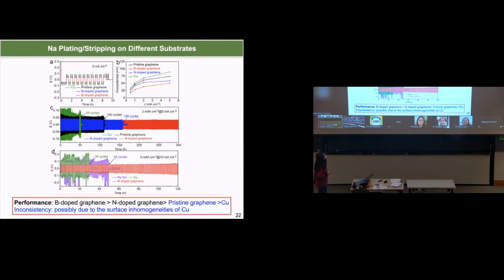Experimentally, we find the boron doped graphene has the highest stability, and it's better than the nitrogen doped graphene, which is better than the pristine graphene, which is better than copper. If you recall, in the theoretical calculation, these two were in the reverse order. We dug further into the reason and found that for the copper surface, we directly used the commercially available copper substrate after we purchased it, and the surface is relatively rough. So this inconsistency could probably be due to the surface roughness of copper compared to all these relatively flat graphene coated surfaces.